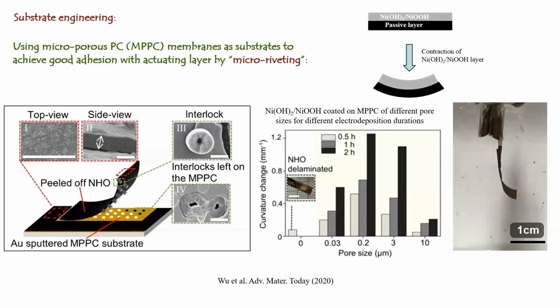So there are holes in such membranes. The pore size can be in this range, so it could go from less than a micron to 10 microns. So these are the pores. And then we deposit these TMO materials on top. Therefore the material can actually be grown inside the pore to serve as rivets, but at a micro scale. We do that because the intrinsic adhesion between these oxides or hydroxides and the polymer is weak.